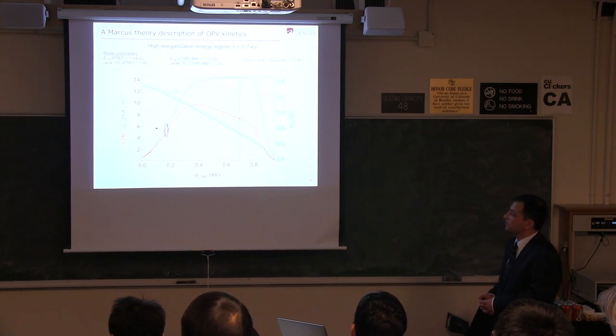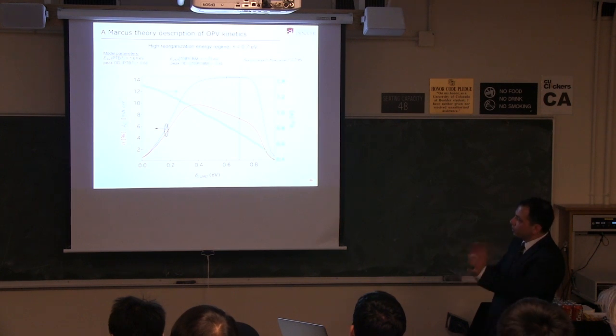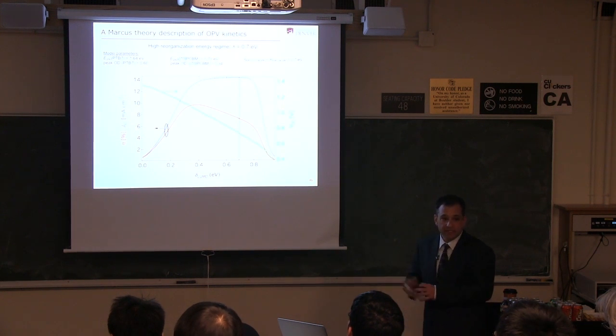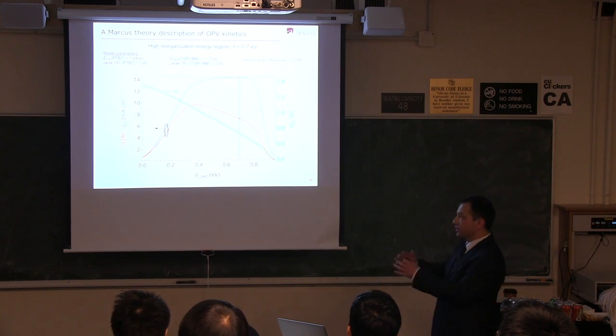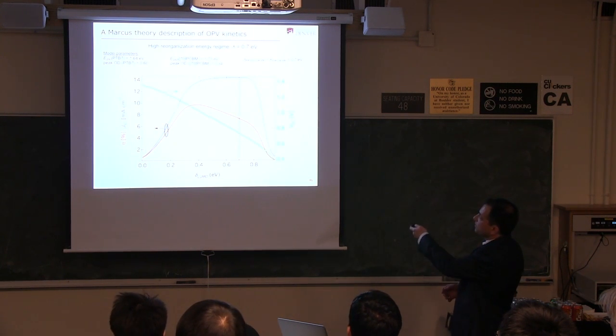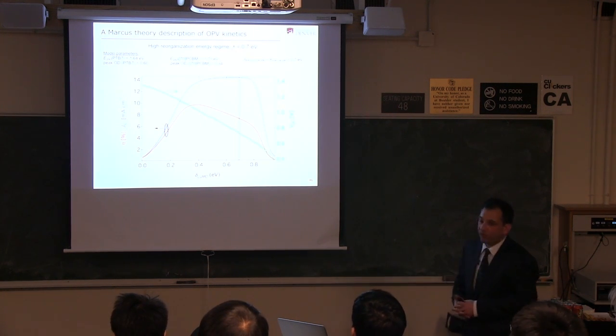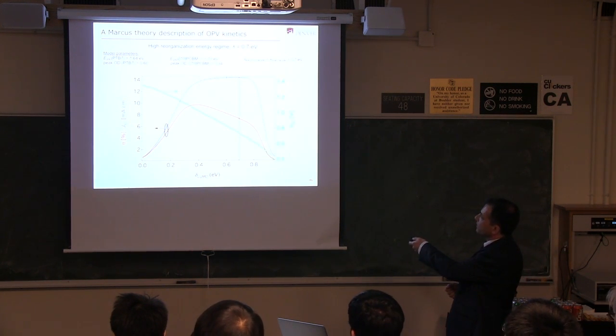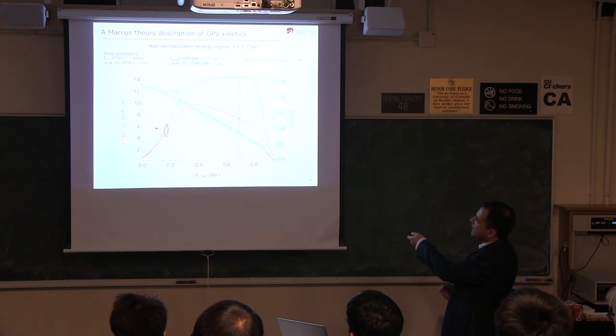Okay, I'm going to skip the rates and just cut to the chase. Those are rate constants, but this is basically the performance of the device. What we can do is take all those parameters and fit them to our existing experimental device, that 7.4% device made from PTB7. We took the spectra that we know very well, and the optical densities we can measure, and fit the reorganization energy and came up with a value of about 0.7. That gives you an open circuit voltage of 0.7, a short circuit current of about 15, and an efficiency of 7.4. So that vertical line is a fit to that 7.4% device.